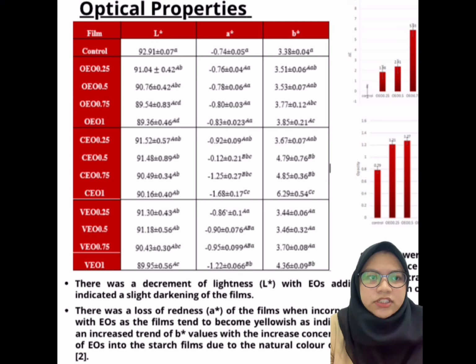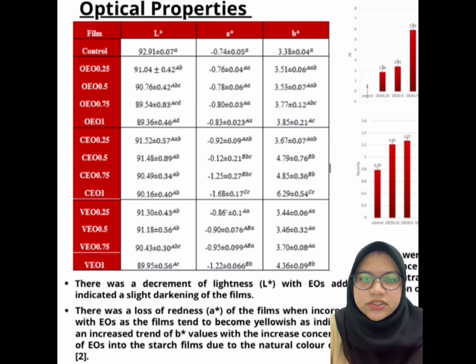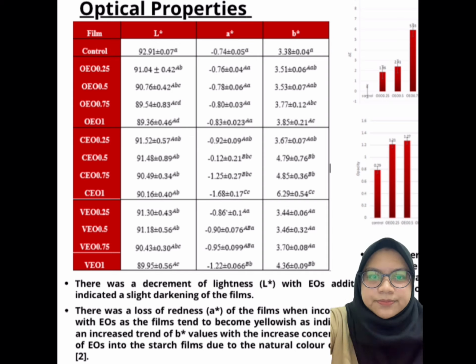Next is the film optical properties. Firstly, as you can see in the table here, there was a decrement of lightness, shown by the L value, with the essential oil addition indicating a slight darkening of the films. There was also a loss of redness in terms of the A value of the film when incorporated with the essential oil, as the film tends to become yellowish, indicated by the increased trend of the B value with the increased concentration of essential oil in the starch film, due to the natural color of the oil.